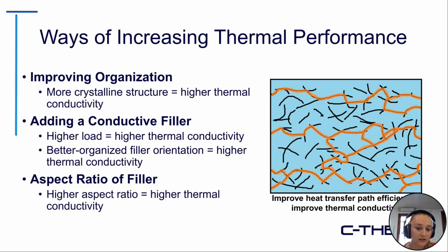So there are a few ways. The first, as we've talked about in the last couple slides, would be to improve the organization. As we just talked about, a more crystalline structure equals a higher thermal conductivity. Another way that a lot of groups we work with are attempting to raise the thermal conductivity is adding a conductive filler. So a higher load of the conductive filler will, of course, result in a higher thermal conductivity.